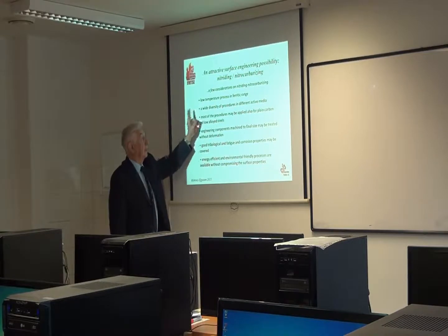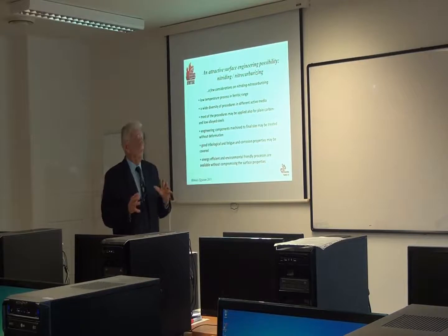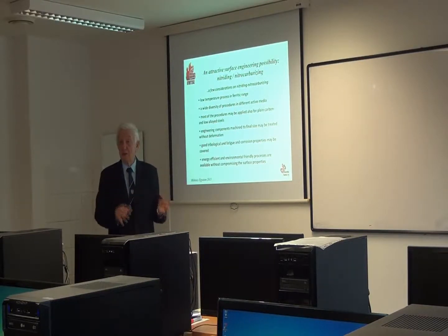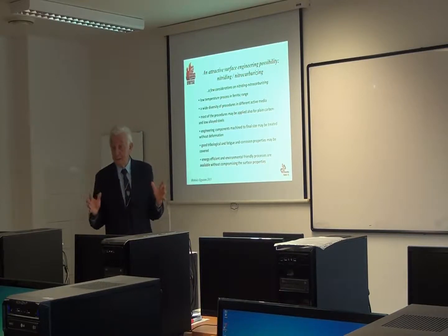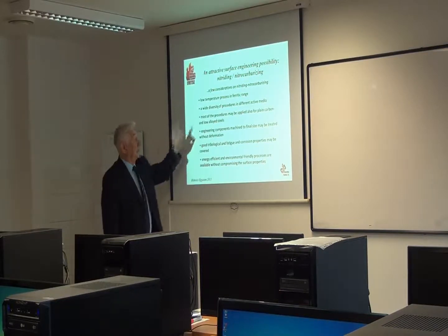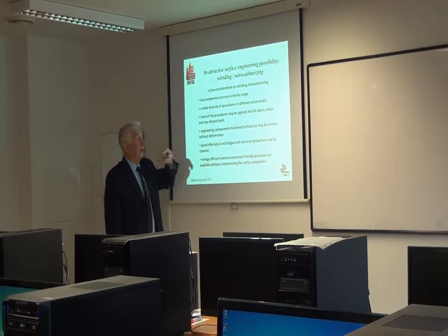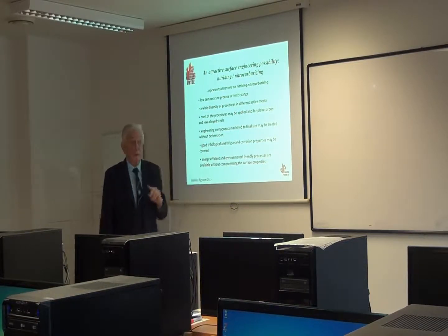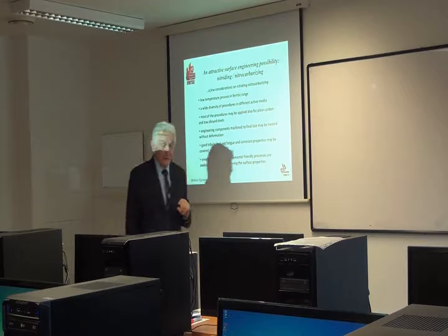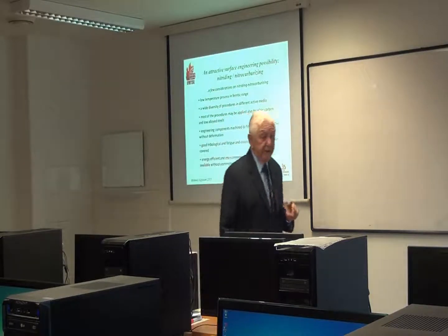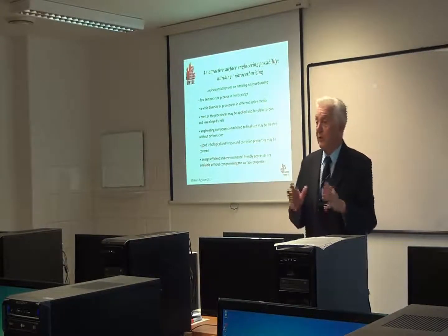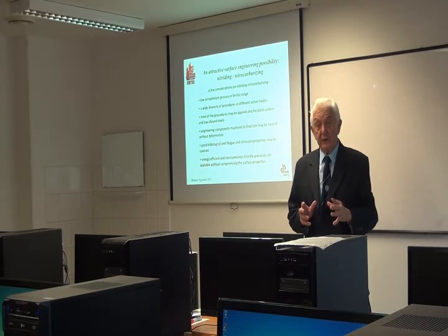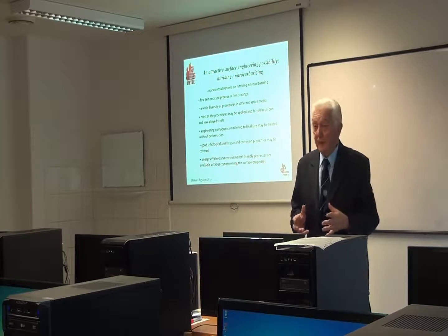Well, then there is a very wide diversity of procedures in different media: gases, plasma, salt baths, so there is a wide range of procedures. Most of the procedures may be applied also for plain carbon and low alloy steels, and this is extremely important. Why? Because still we try, because of cost considerations, to use low alloy or plain carbon steel whenever it's possible.